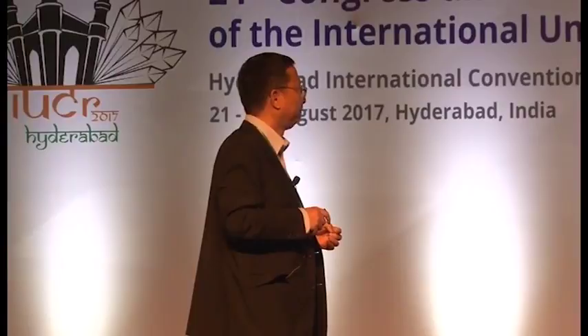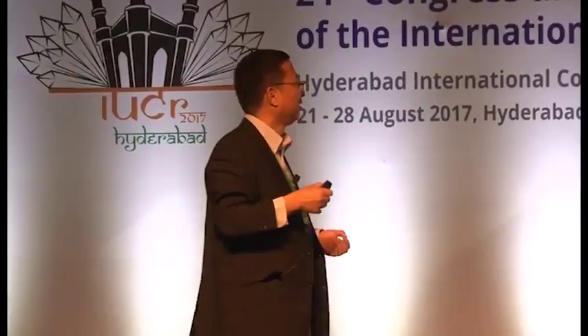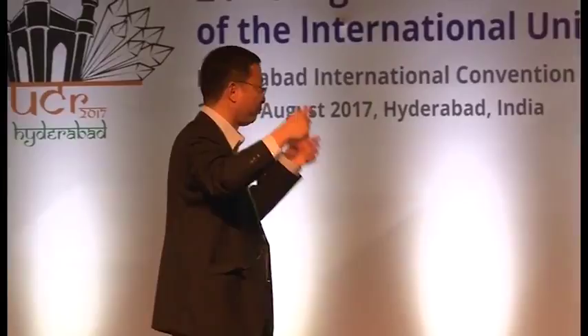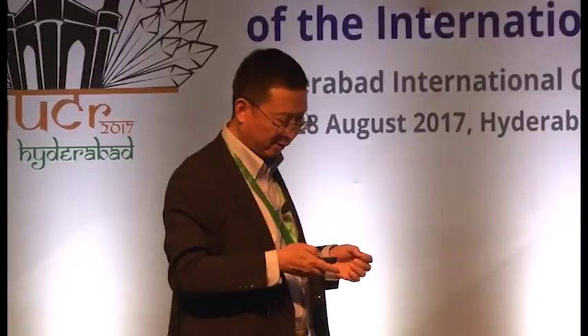As I mentioned before, for dysprosium, the Ising limit of electron density is prolate. For dysprosium compounds, the ligand field from the axis directions is better. So here, actually, the oxygen from beta-diketone is strong compared with bipyridine and compared with the CP ligands, it's strong charge density, so it determines the easy axis direction.